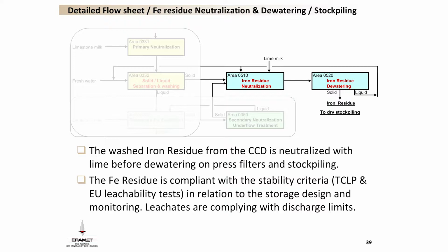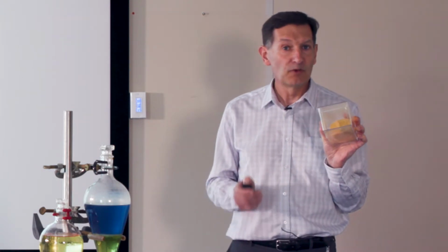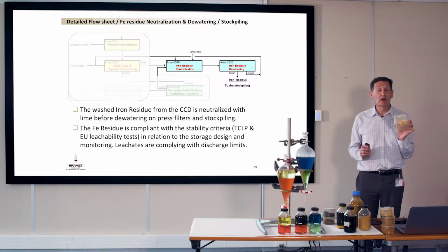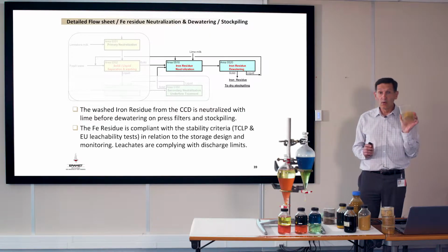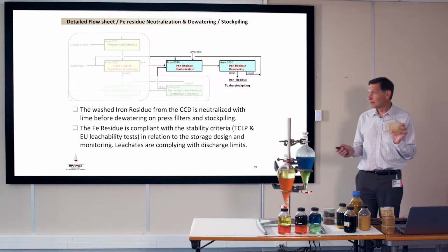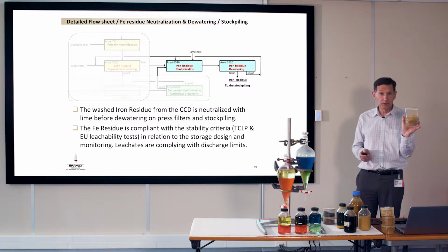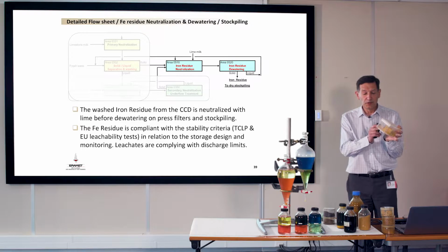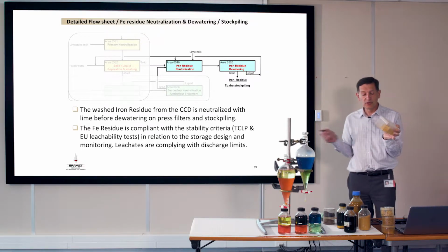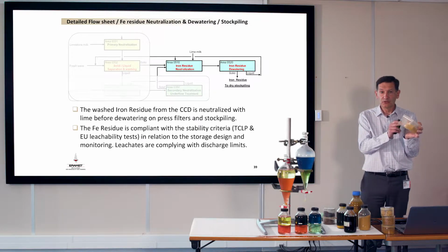I remind you that the ore is an iron ore, and for 1 ton of ore there is only 17 kilograms of nickel. All the remaining part is iron, and such a process is a plant to produce residue. In this residue, you add some sulfate due to the fact that you have precipitated jarosite, and you add also gypsum, calcium sulfate.